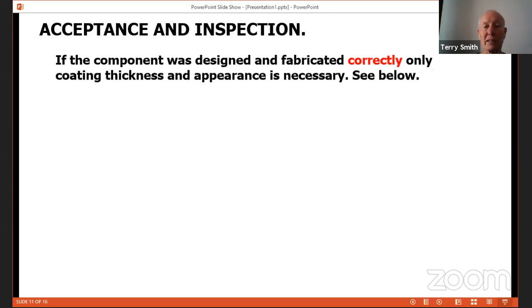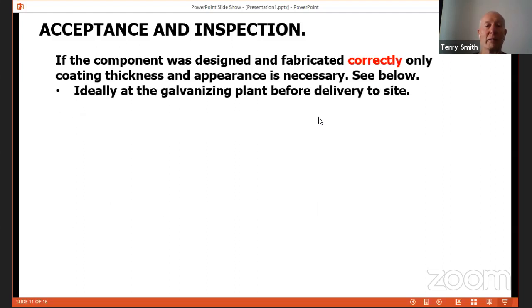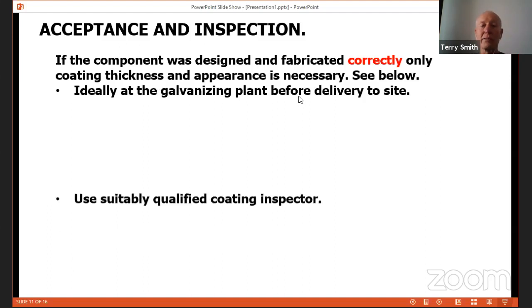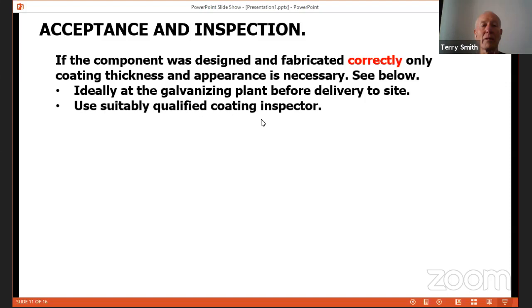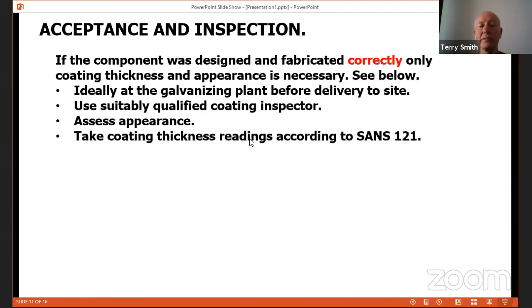Acceptance and inspection. If the component was designed and fabricated correctly, the coating thickness and appearance are the only things that are necessary. Ideally, this inspection should take place at the galvanizing plant before delivery to site. Use a suitably qualified coating inspector. And just based on that, I know the Hotdip Galvanizers Association has courses for this purpose. Assess the appearance of the item, take coating thickness readings, according to SANS 121.